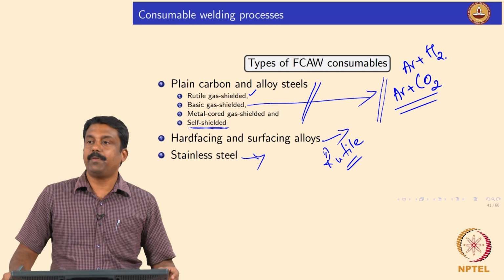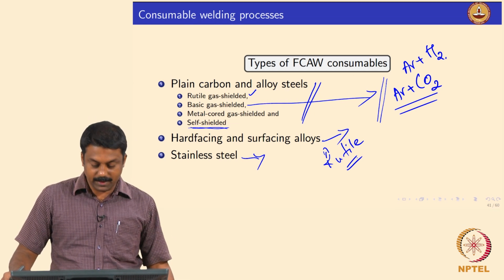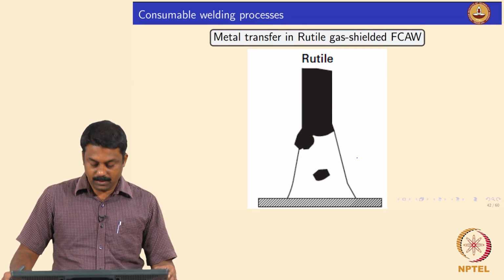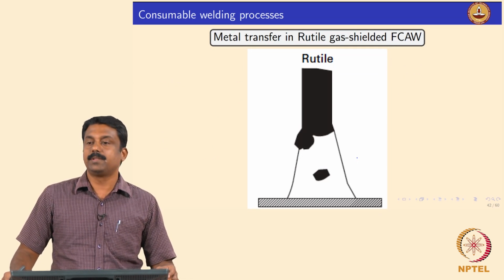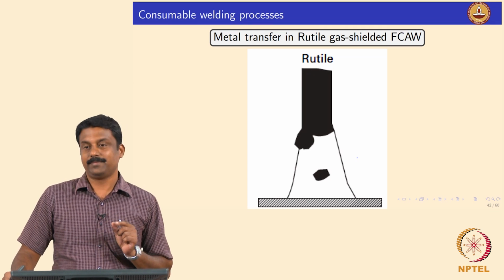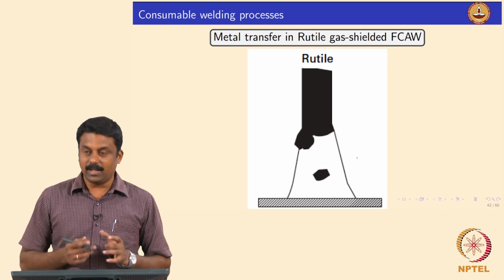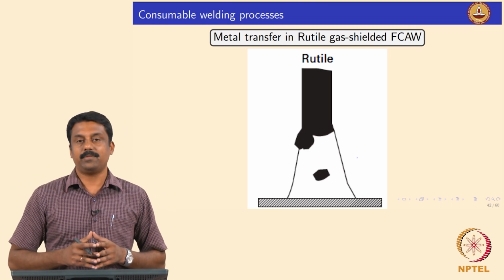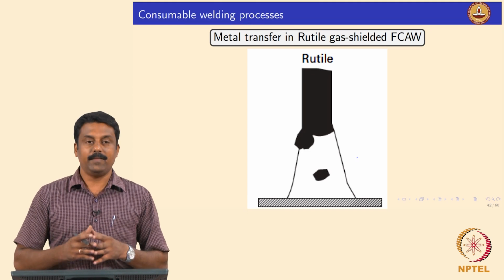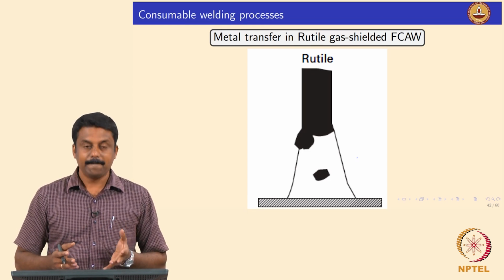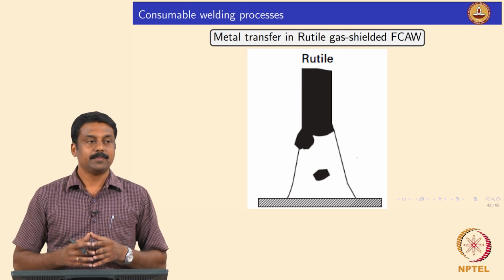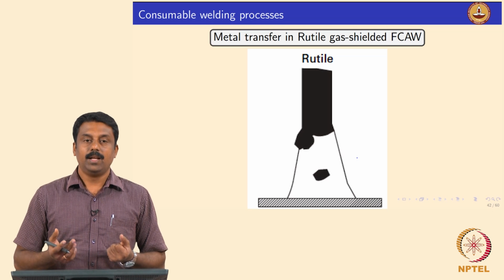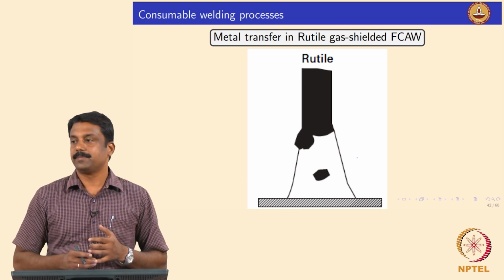Good. Any questions so far? Then we will move on to the metal transfer in this process. So, in most of the rutile based electrodes, the metal transfer is the same as GMAW, because rutile reduces surface tension. So, the droplet can be transferred with smaller diameter, right, and you will have a simple free flight droplet transfer, and the droplet diameter can be much smaller, because titanium oxide favorably changes the surface tension, and that improves the transfer characteristics, right.